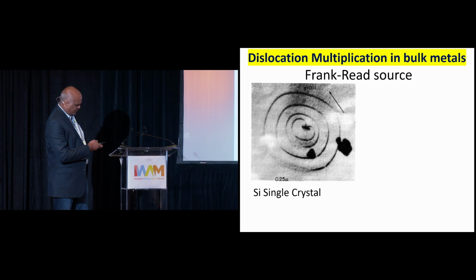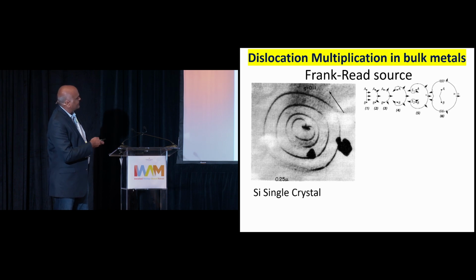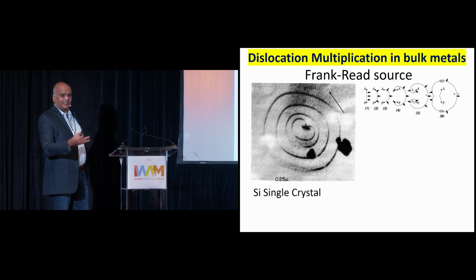So the Frank-Read source basically is if you have a dislocation line like this, if it's pinned on two ends - or it doesn't need to be pinned, but it can have only shear stress on this particular segment - so what happens is once you apply stress, it bows out, and after a while it becomes unstable and punches out a dislocation. And this is what you can actually see in this thing, right?